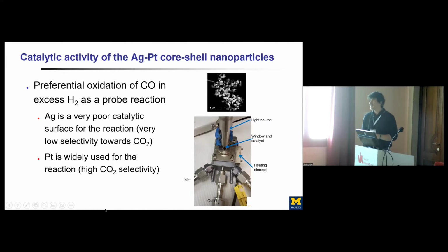But the idea is that you really have to find precursors of platinum that under electrochemical conditions can uniformly deposit on silver. And the ones that we have commercially available, basically salts of platinum, don't have those properties. You have to really play with creating new precursors of platinum that would allow for a really soft landing of that platinum and reduction under electrochemical conditions that allow for the covering of the entire surface.